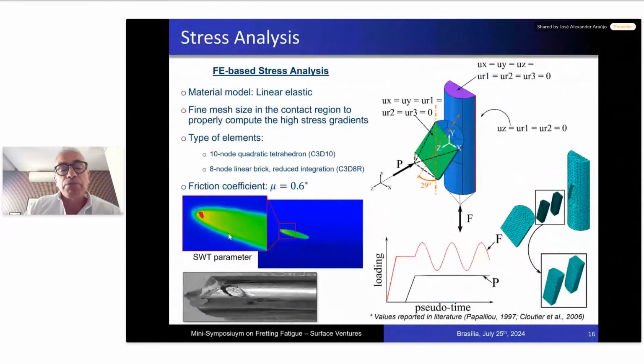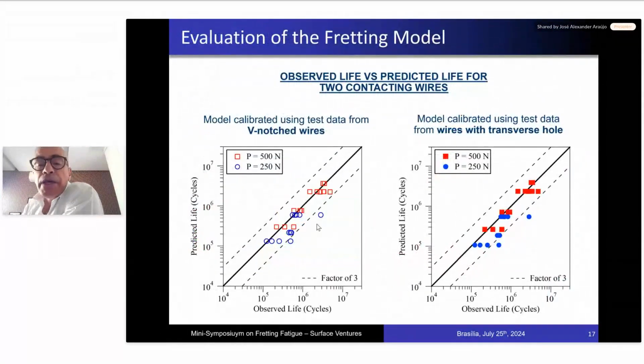Then we did this finite element simulation of the wire itself. You can see that using the Smith-Watson-Topper parameter, the most stressed point coincides quite well with the position of failure in the lab. And then we apply this methodology to obtain estimated lives. And in these two graphs, what you see is the estimated life for normal contact load of 250 and 500, okay, blue for 250, red square for 500, and in the left graph, I have the estimated life against the observed life when I use the S-N curve obtained with the V notches. On the right is the same, but I use the S-N curve considering the transverse hole notches, and you can see that the estimates are quite nice within a factor band of 3, okay?